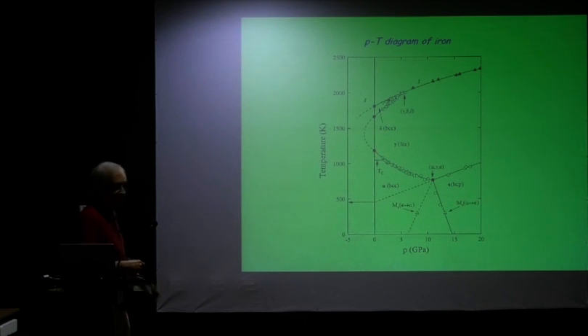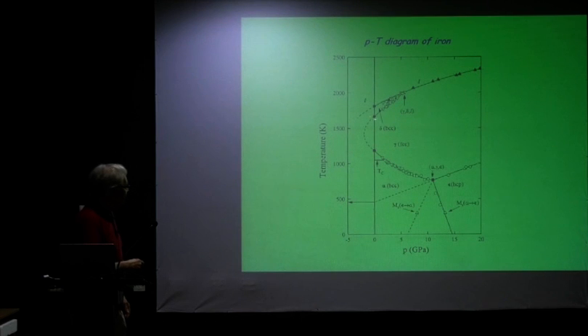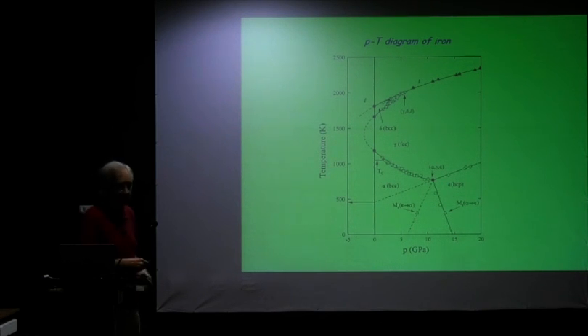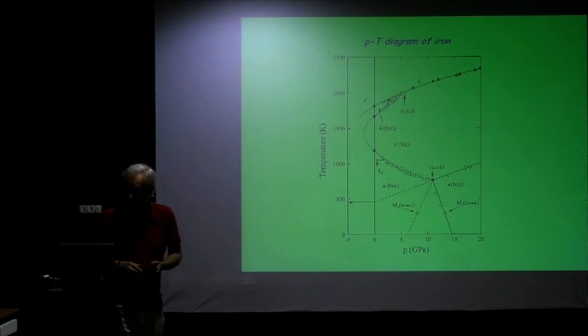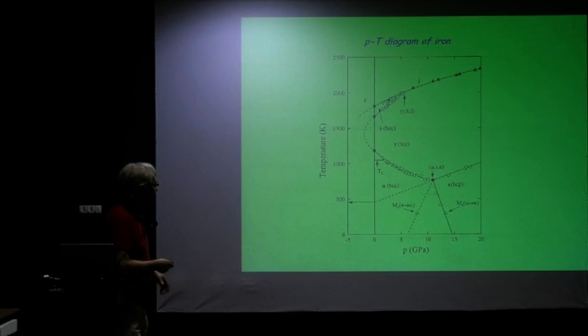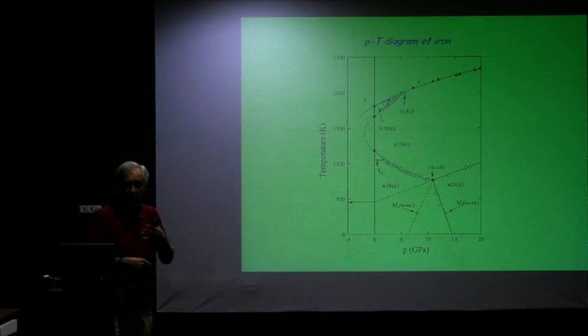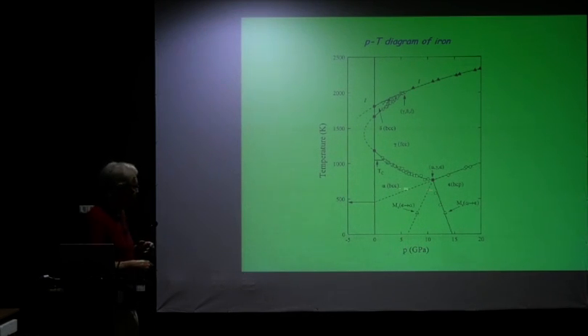The next is, what would happen if it were possible to go to negative pressures? That is, if we were able to expand the volume somehow. This is a body-centered cubic phase. It's stabilized purely entropically, and this is the BCC phase, which is stabilized by the magnetism. So if it were possible to open up the volume, or to increase the volume by applying negative pressure, hypothetically of course, then this line would have most probably closed in as such, so that the FCC phase would no longer be stable and only the delta phase would be there. So these are things that we can sort of acquire information on, what could be going on in iron under different conditions. Okay. Are there any questions up to here?